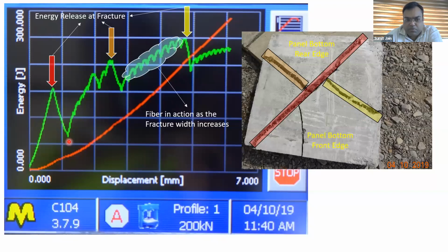Then the first fracture happened, and again things started building up. Now you can see slight waviness in the curve. These are fibers which are getting into action. They go to a particular limit, then again there is a drop. Again they rise up, again there is a drop. This is the place where the displacement is increasing at a much higher rate compared to the load. Here you can see all the waviness, this is the ductile behavior which has started in the specimen. These are fibers in action as the fracture width is increasing.